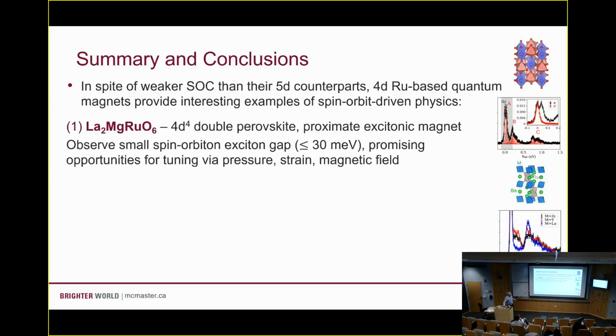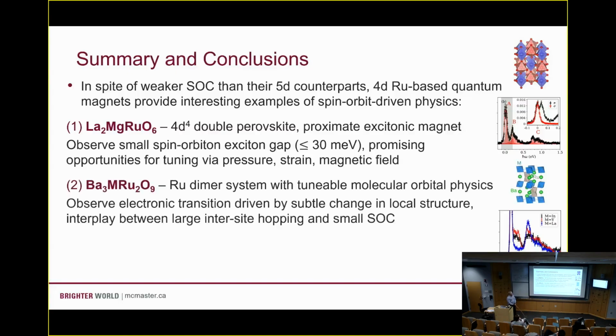We had this lanthanum magnesium ruthenium oxide double perovskite, okay, which gave us a small spin-orbit exciton gap with the prospect of tuning to get into this excitonic magnetic state. We had the ruthenium cluster magnet, which gave us the tunable molecular orbital physics. We got this electronic transition that was driven by the combination of large intersite hopping, small spin-orbit, and then these very small changes in local structure.